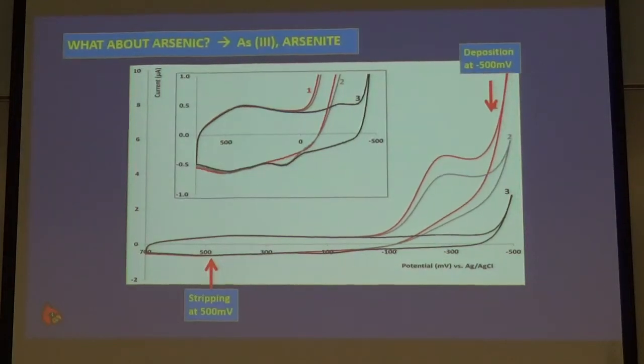Another electrochemical technique I'm going to show you is called cyclic voltammetry. What we do is we start at a potential and scan the potential out negatively. When we get negative, something gets reduced. If we just take a blank solution and scan at a gold electrode over this potential region, we get this one wave, this red wave. That corresponds to the reduction of oxygen. Unless you remove it, oxygen is always present in solutions.